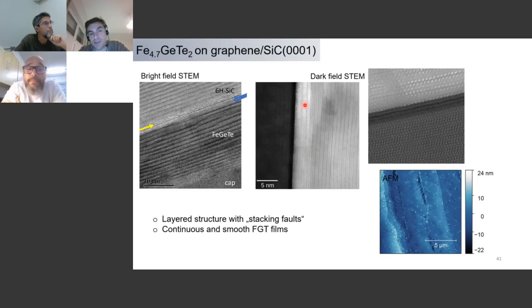And indeed we see this Curie temperature around 390, 380 Kelvin, which is much higher than other groups have been reporting. And we believe that this is related to this kind of disorder that we have now that allows us to have this higher TC. And we are definitely very interested in that. We are looking into that nowadays. First, we want to understand what these stacking faults are doing, for instance, to magnetotransport and ferromagnetism. But in addition, we want to control that even better, because at the end of the day, we want to be able to get rid of this kind of stacking faults. Even if we lose in TC, we want to try to improve that.